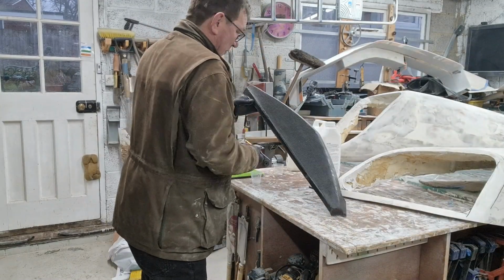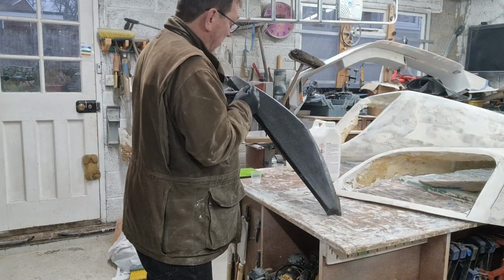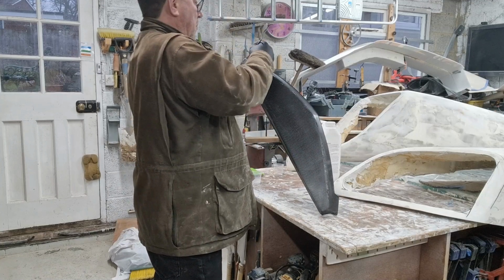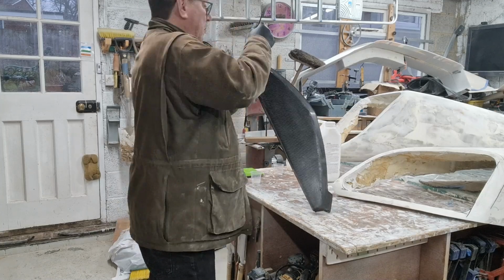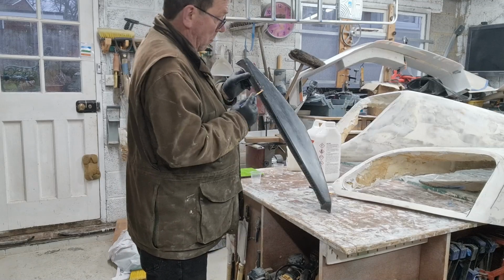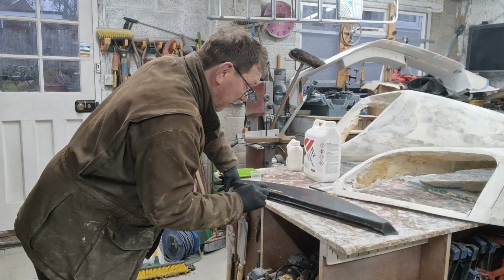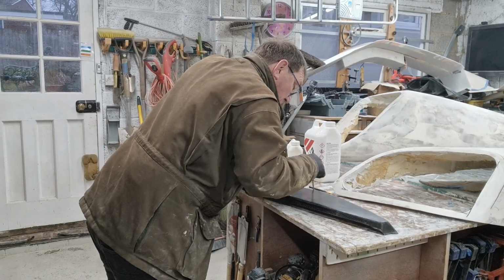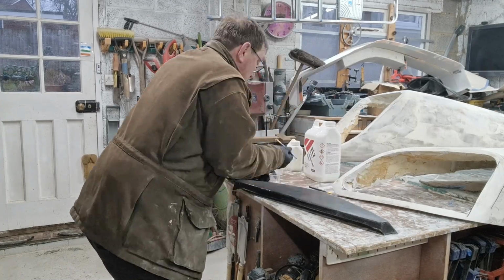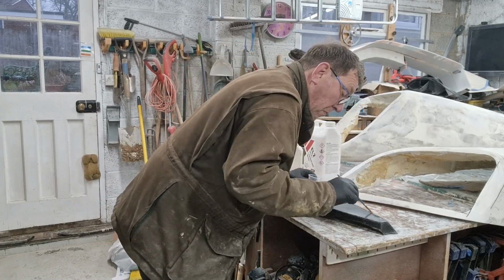Solving the defects was easy. Those crystalline looking ones were bubbles inside the resin. Used a Dremel to just sort of grind out the area of resin around it, so they ended up looking like those little pock holes in the first one. The white bits on the top will actually need some panel wipe to get the dust out, and they also look like gaps in the resin.